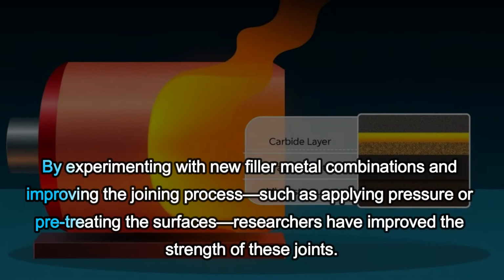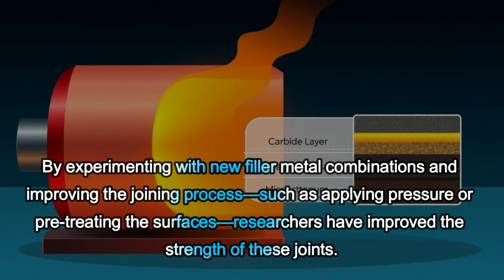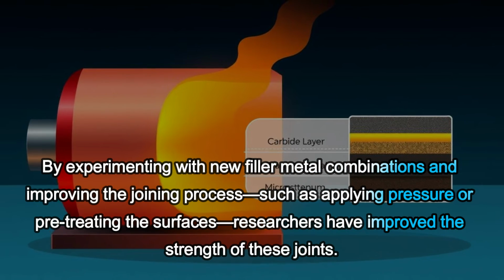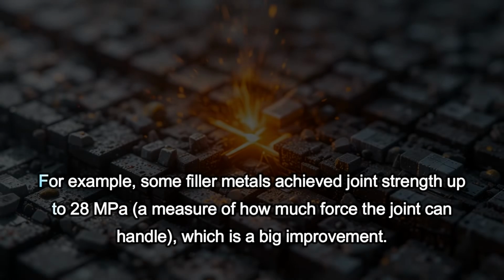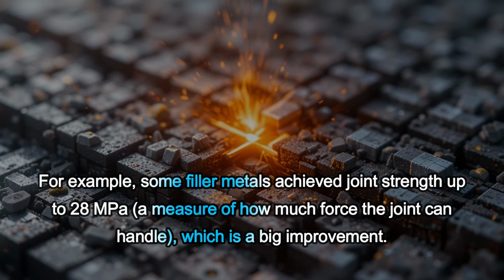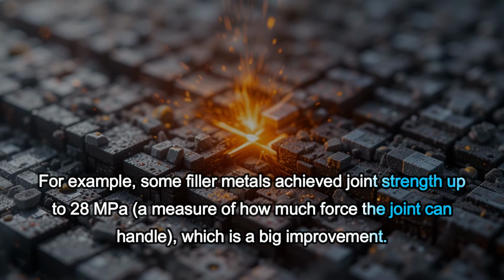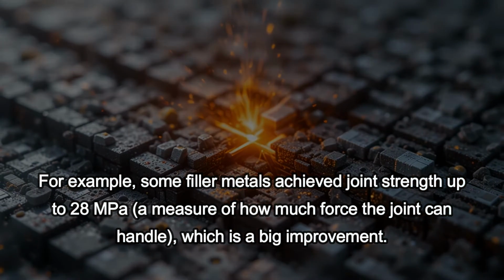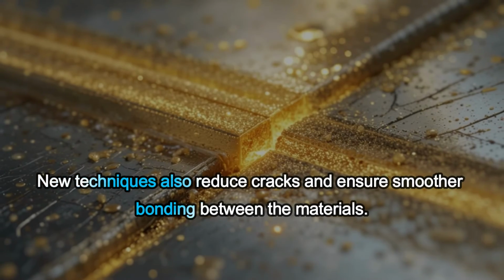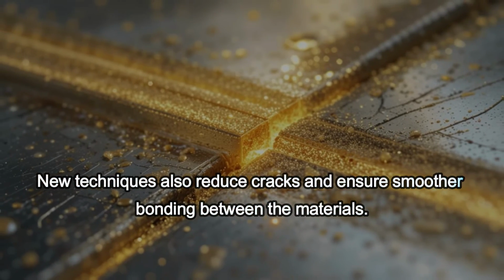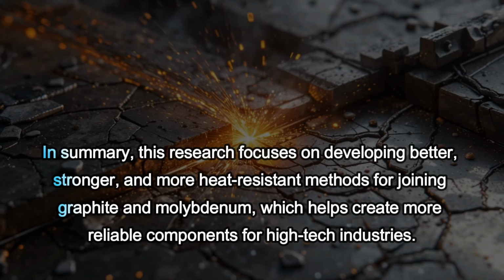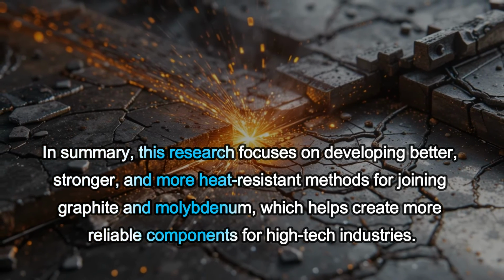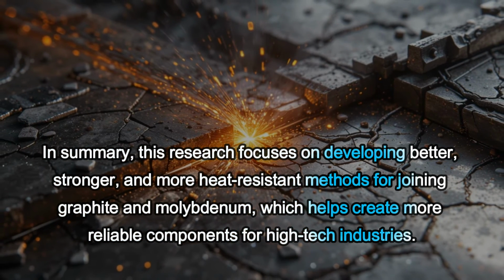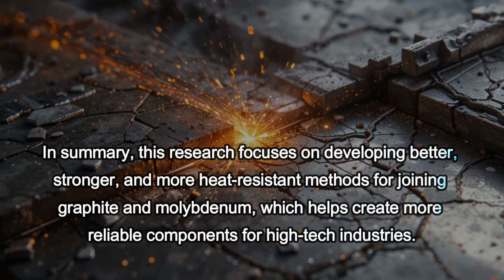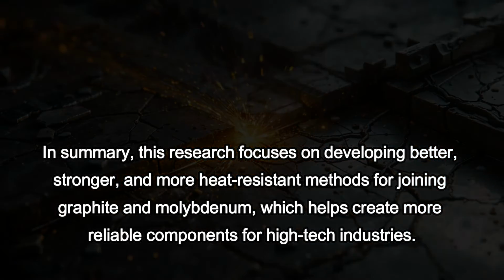By experimenting with new filler metal combinations and improving the joining process, such as applying pressure or pretreating the surfaces, researchers have improved the strength of these joints. For example, some filler metals achieve joint strength up to 28 MPa, a measure of how much force the joint can handle, which is a big improvement. New techniques also reduce cracks and ensure smoother bonding between the materials. In summary, this research focuses on developing better, stronger, and more heat-resistant methods for joining graphite and molybdenum, which helps create more reliable components for high-tech industries.